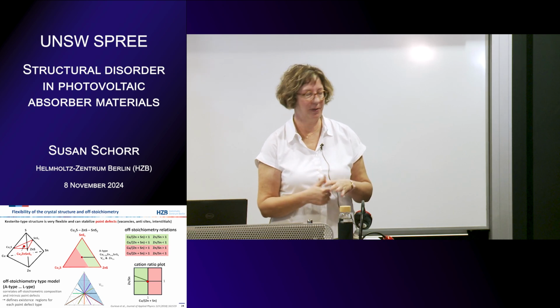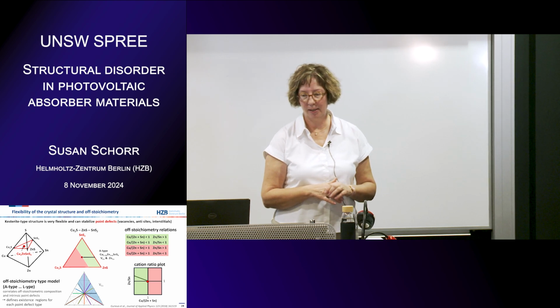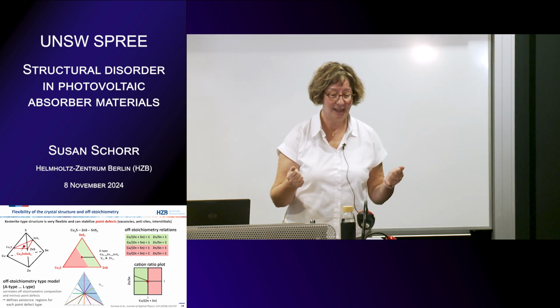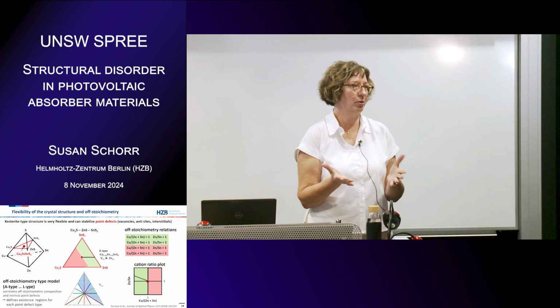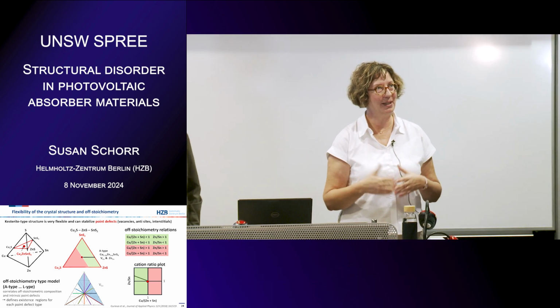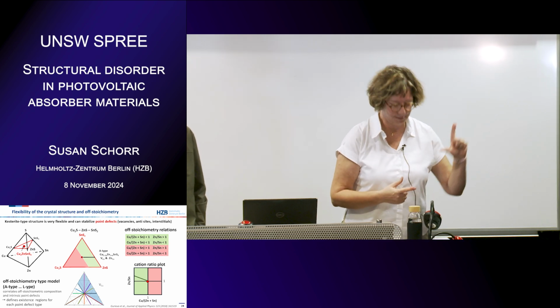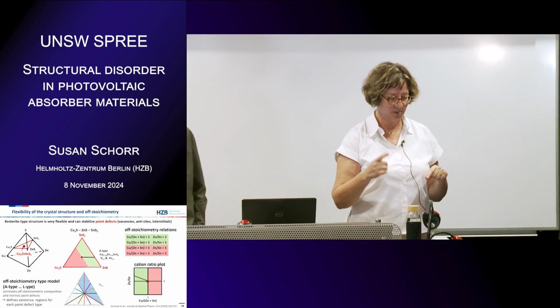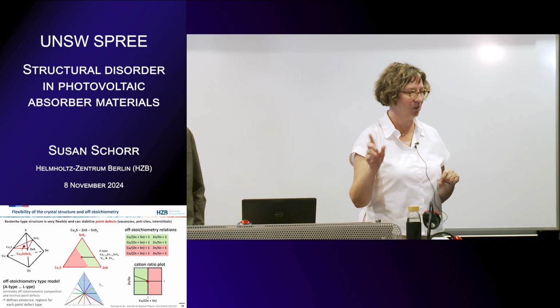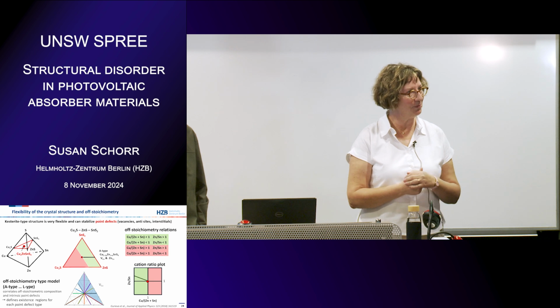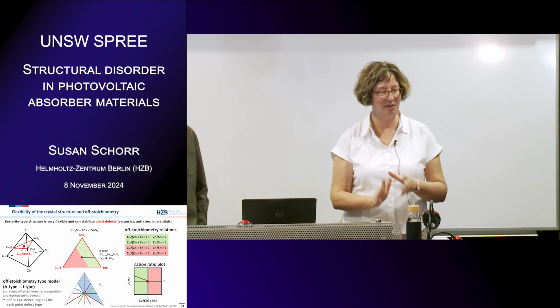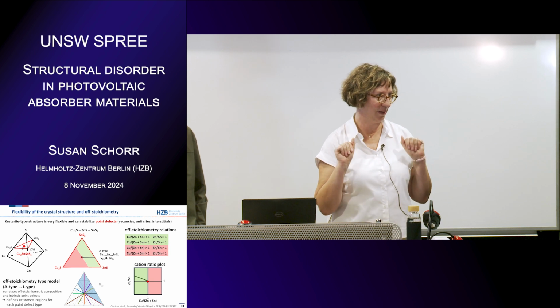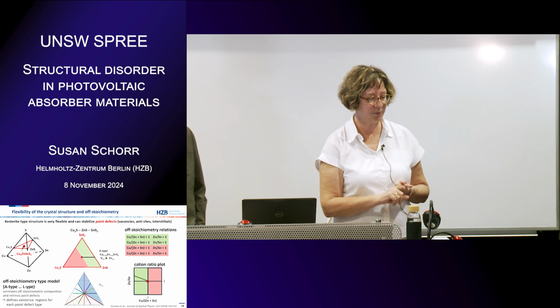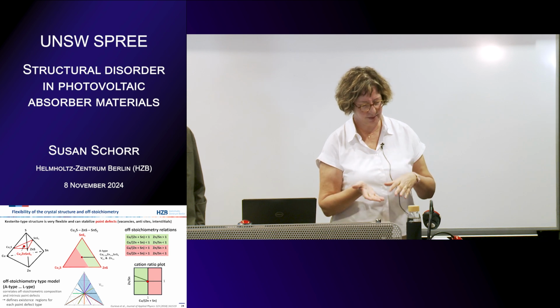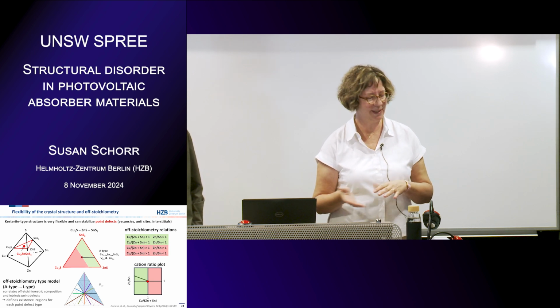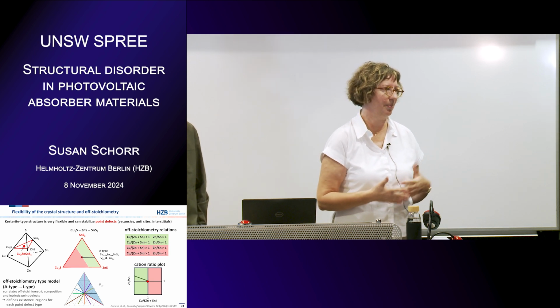So, as I said, we also studied chalcopyrites a lot, also on powder, of course. At conferences we were asked, how could you be sure that in the thin film it's the same? That's why we made one study, in principle two, about copper indium selenide thin film. The colleagues at the PV-Combi made a big thin film for us and they scratched it. And then we measured the scratched thin film as a powder. We did it for copper indium selenide and, I think, a sodium doped copper indium selenide, and we found the same defects as in the powders.